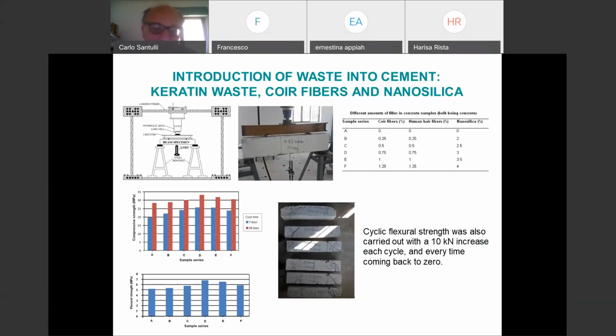You can find a very large number of these kinds of studies trying to see whether introducing waste in concrete reduces the cost while keeping the same performance. Here, what they have done is compressive strength, of course, after 7 days and 28 days, and the compressive strength increases with time. I assume that at 28 days we have to stop. But if you want to leave your wall covered for 1 year, that would improve the compressive strength. But the law requires 28 days, apart from particular situations. In normal situations, it requires 28 days.